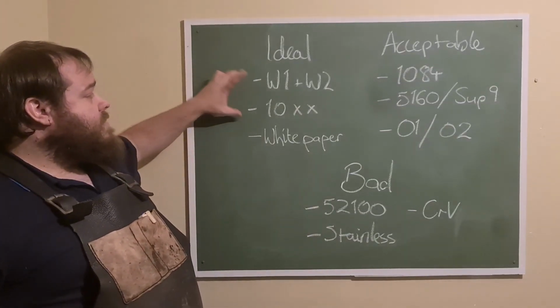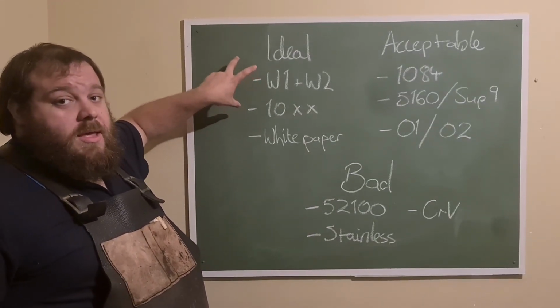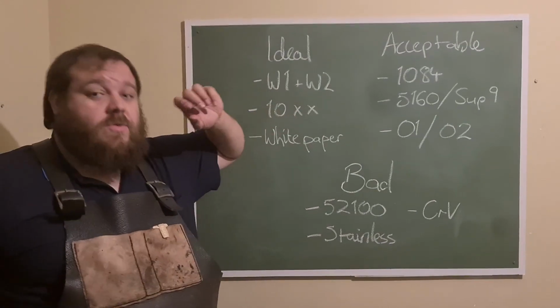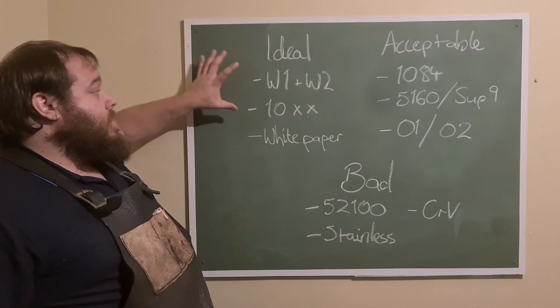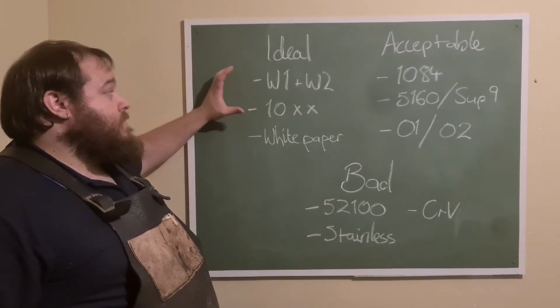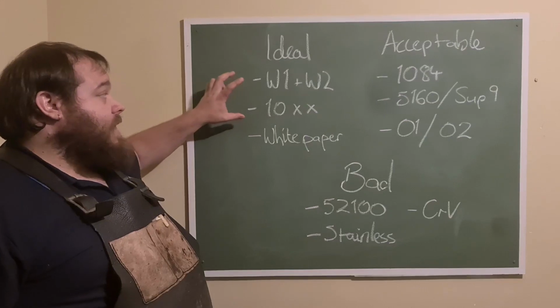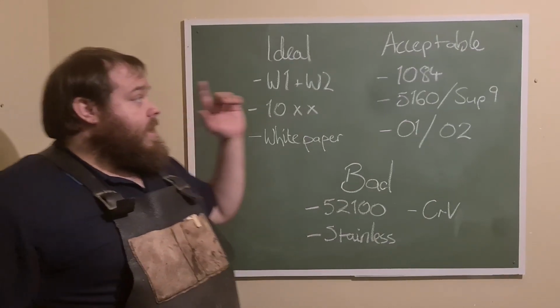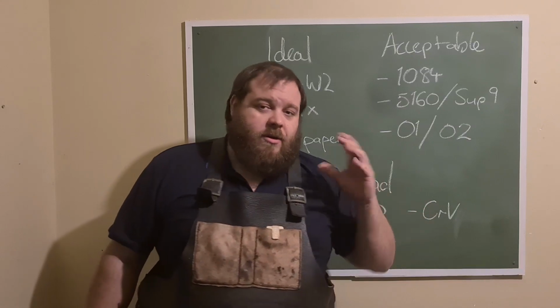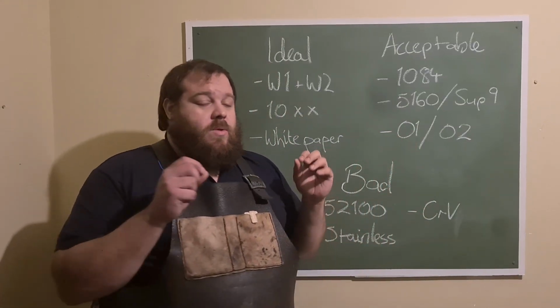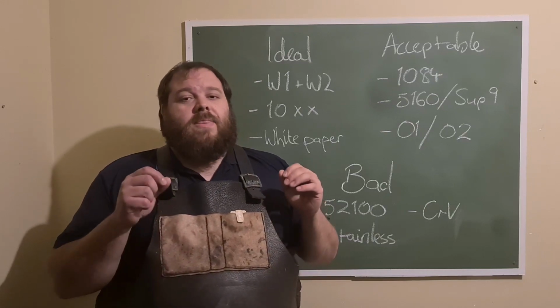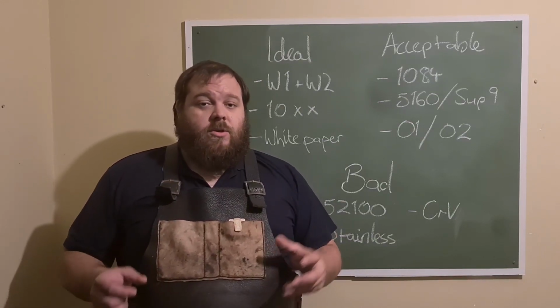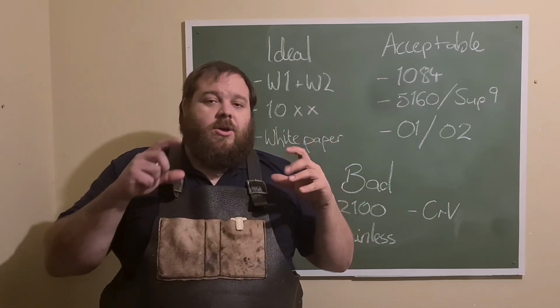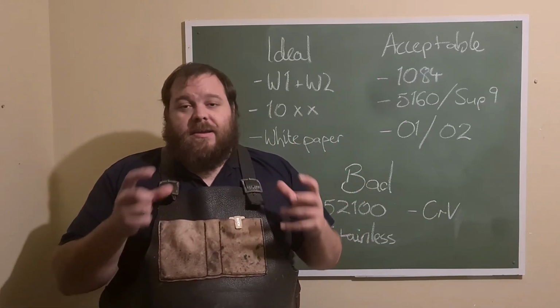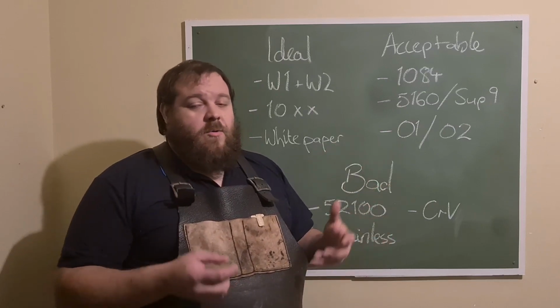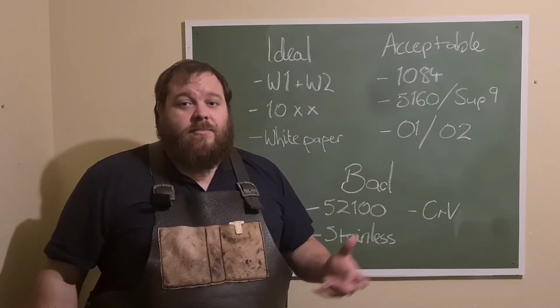So your best bet, if you want to make a good Hamon in your steel with ashi, when we're talking about high activity Hamon, then you want to go with files. But otherwise, try and purchase steel from a distributor that actually makes this stuff. In the acceptable category, why I say acceptable and not ideal is because you can create Hamon in these steels, but they will not be high activity Hamon. You won't get the beautiful, flowy, ghostly ashi that you'll see in things like katana, and in the very, very well-made knives by people like Glenn from GC Custom Knives.